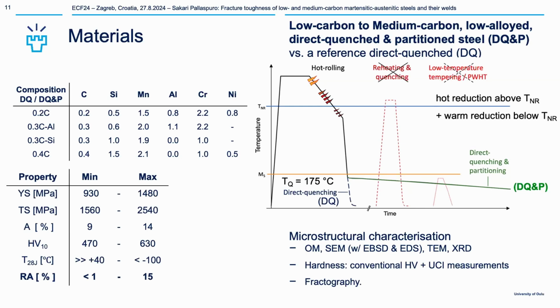So for these materials, we have a yield strength range from 900 to 1500 megapascals, tensile strengths from 1500 to 2500, roughly 10% of elongation, still quite moderate, but sufficient for these strength levels. Hardness from a bit below 500 to 600, and the retained austenite content from a bit below the detection limit to 15.